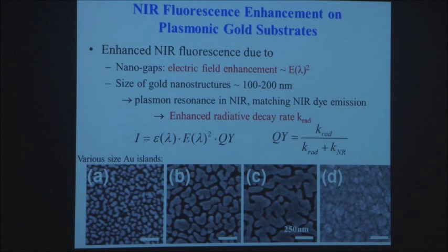And so the mechanism of this fluorescence I mentioned is plasmonic enhancement. What we did was to vary the film structure, so you can actually make the size of these particles different. Over here it becomes a continuous film. What we found is that these two types of films in the middle can enhance fluorescence, but these guys here actually have some quenching effect.